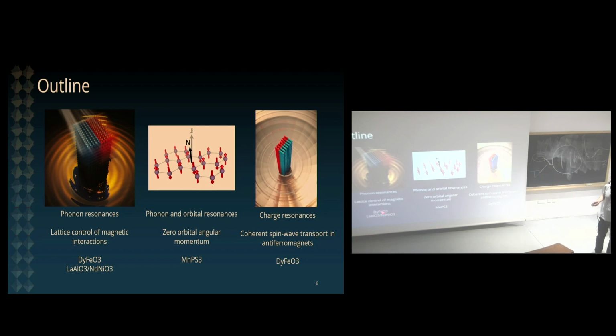And then we're going to put an epitaxial film on top of lanthanum aluminate. We will excite these strain waves, and we'll see what's going to happen to the properties of this thin film. So this will illustrate a little bit what can happen when we excite phonons resonantly in complex oxides. And we will apply these ideas to the study of a very interesting antiferromagnetic system that is called dysprosium orthoferrite. That is an interesting material because it's characterized by multiple magnetic states that are possible, that are close in its configuration space.